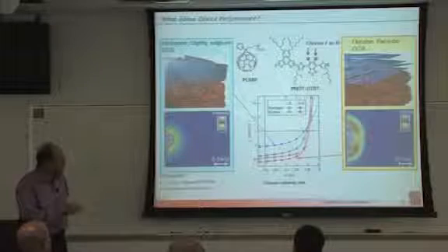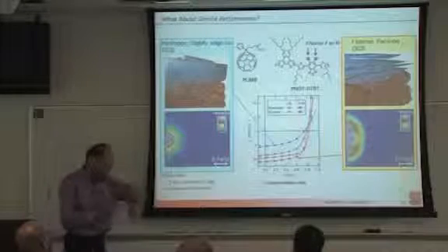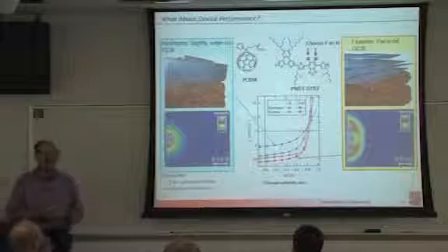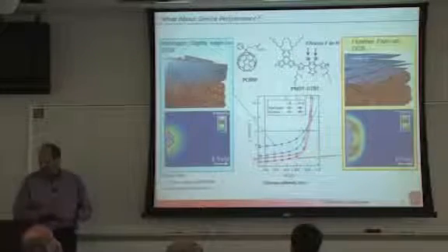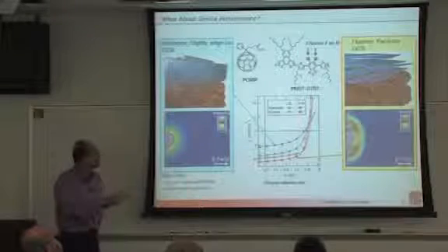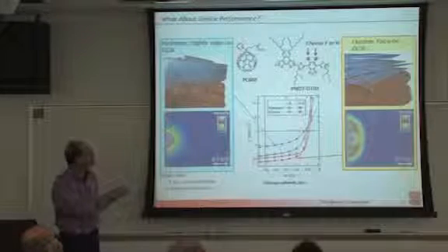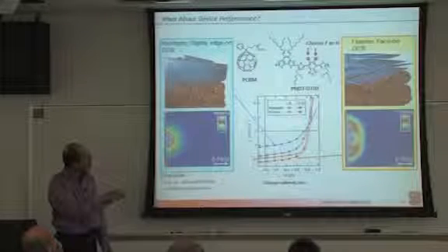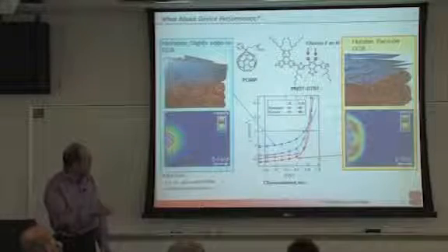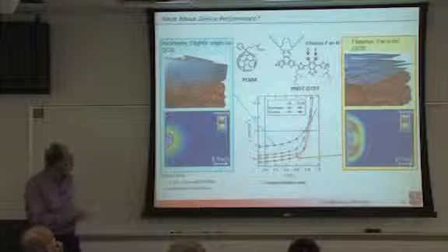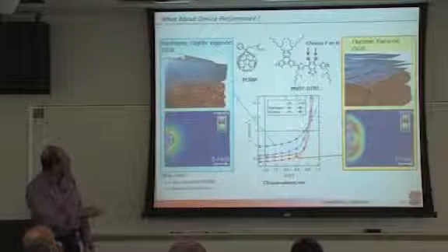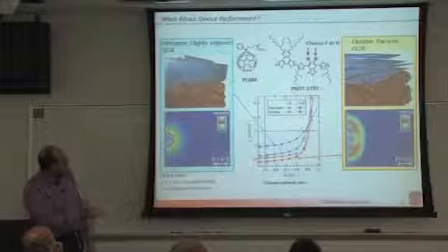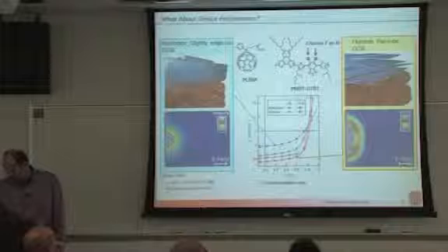So now let's compare this. We observed this anisotropy. We figured out where it comes from. We understand the energy dependence. And so now let's go back to the device performance. So I have the material with and without fluorine, and I can cast from chlorobenzene or dichlorobenzene. I get 4 devices. The worst device has the slightly edge on. This device has the face on.